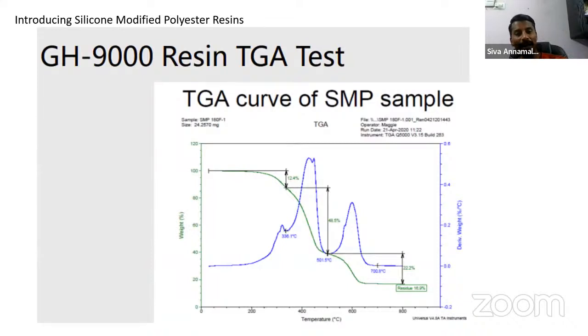You follow the green line. From 100%, after 200, 300, 400, even 500, the product does not suddenly come down. After 300, it slightly comes down after a long exposure. Even after 600, it is able to stay. The residue is only 12%, even at 600 degree and 800 degrees Celsius.